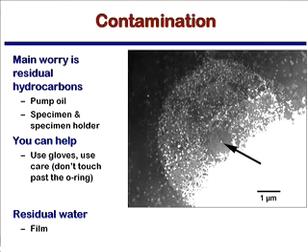One of which where there had been no imaging with the electron beam, one of which where there had been a little bit of imaging, and one of which I'd had the beam on the whole time. And so what this is, we have different levels of carbon contamination, and it turns out that if you have just a little bit of residual carbon, it can help this evaporation process happen. But if you're using the electron beam, it looks like you're creating a thin film of carbon that's thicker and there all the time and suppresses this phenomenon.